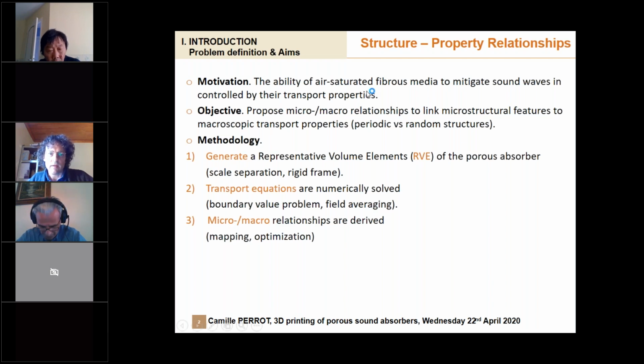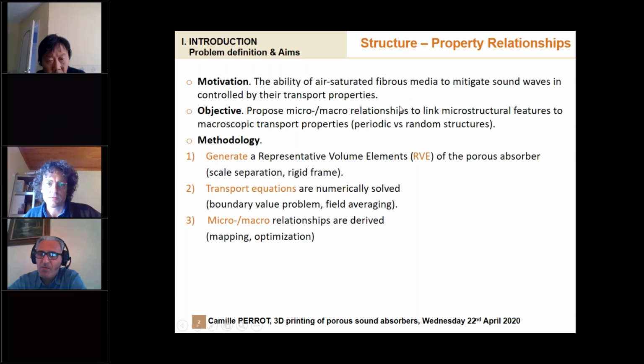The motivation is that fibrous media, foams, or granular media are known to be able to mitigate sound from their microstructural and transport properties. So basically, we are interested in linking microstructures with transport and acoustical properties, whether we have a periodic or random microstructure. The problem will be, in a way, easier to deal with for 3D printings, because in essence we are dealing with periodic microstructures, and you will see that it's convenient for the classical numerical methods, which are now well established in the field.